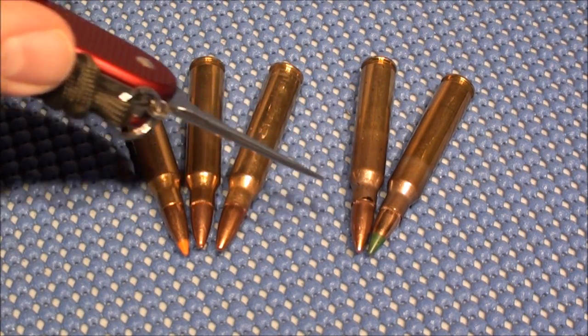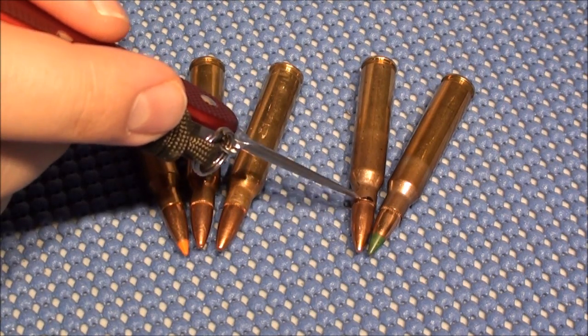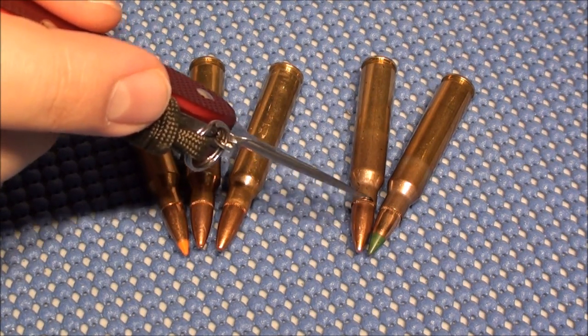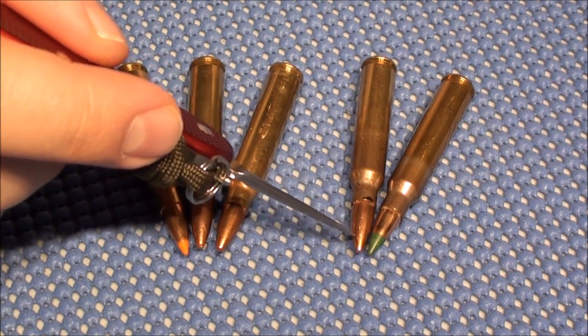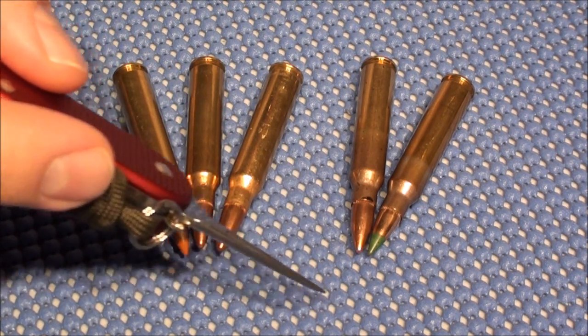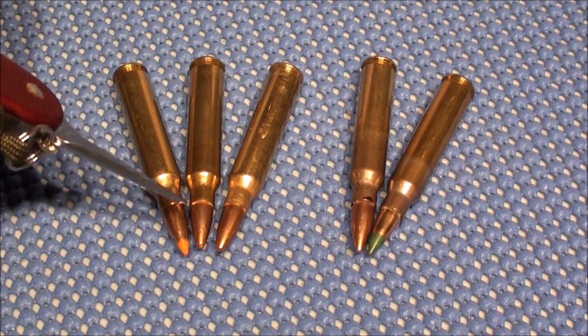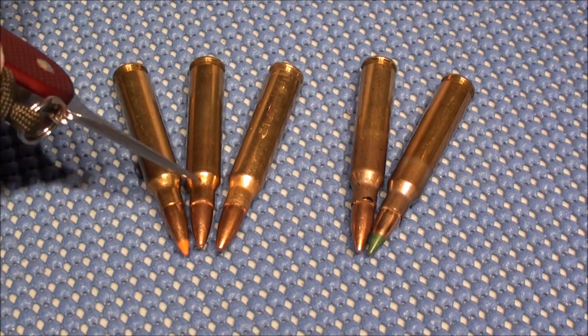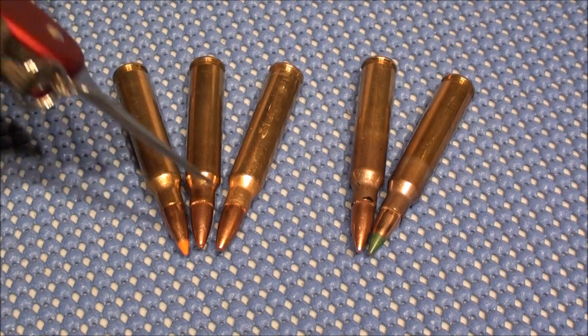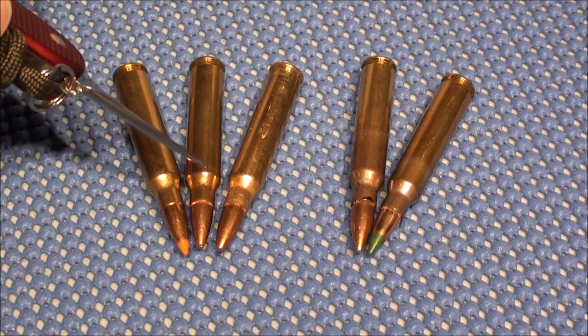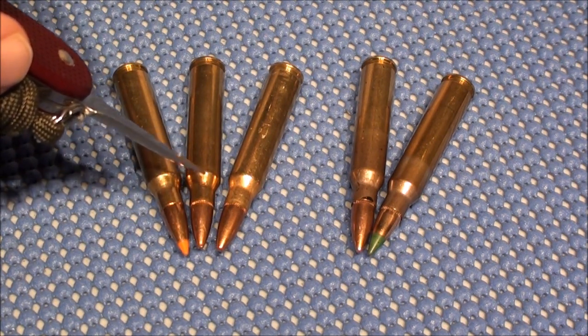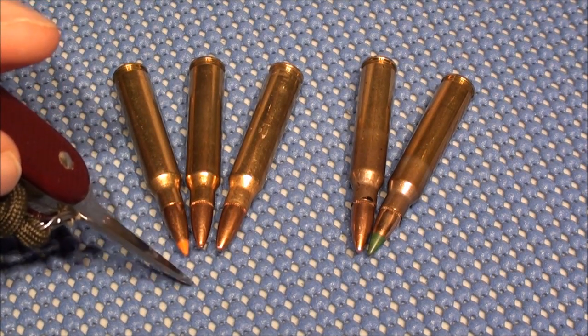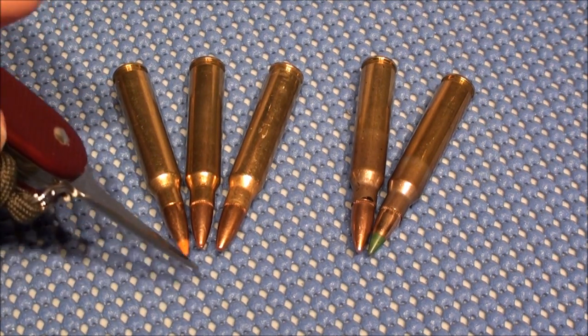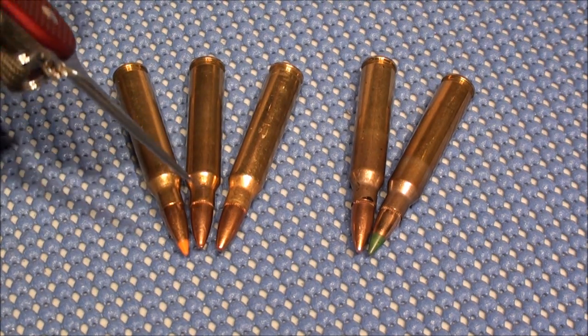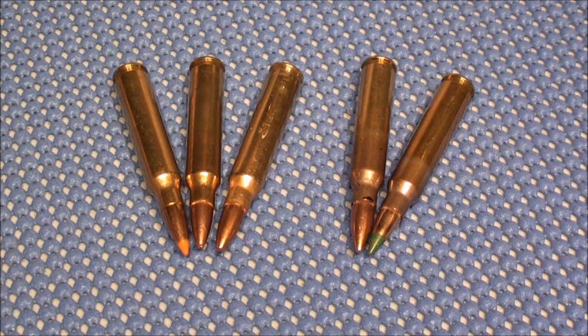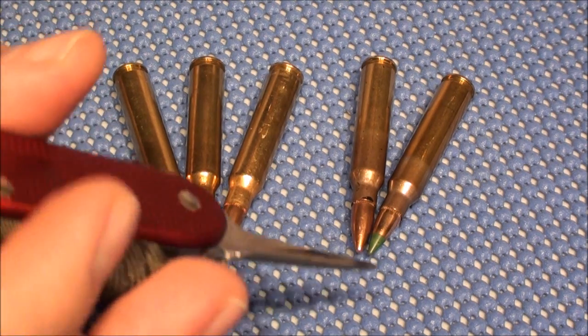Now if you put that same round into a .223, there's less jump between the bullet ogive, which is the curve of the bullet, and the rifling. And so it hits that rifling sooner and therefore builds up more pressure inside the chamber. So you start off with a higher pressure round and then add peak pressure to it because of resistance or less jump to the rifling, and you're looking at a very dangerous situation. So that's one of the major differences between the chamber of the 5.56 and .223.